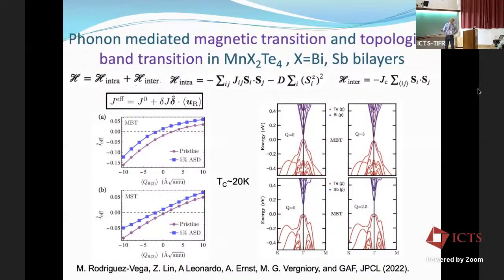And one additional ingredient that comes along for MBT that we did not have for chromium triiodide is that there's a topological transition in the bands. So this system in equilibrium has interesting physics associated with the parity of the number of layers, whether it's even or odd. So odd layer systems have finite Chern number, even layer systems generally don't. Here we have even numbers of layers, bilayers, but when we change the system from antiferromagnetic to ferromagnetic, we end up effectively making it odd layer-like, in that there's a finite Chern number that appears that you can see via a band inversion around the gamma point.